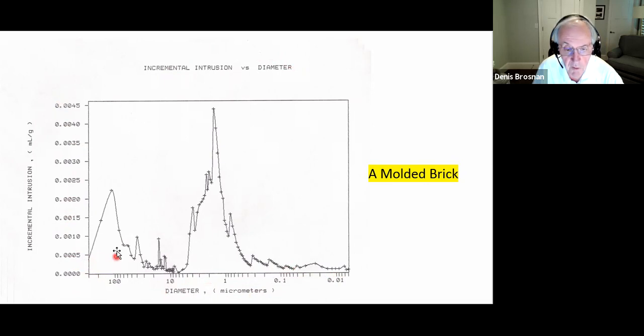If you look at this in increments, we can see that at fairly large pore sizes in this particular brick, we had a band of pores around 100 microns. And as we got down to the smallest band in the area of 1 micron or so, less than 10 microns, we got a large band. Very typical for a brick product. This is a bimodal pore size distribution. Bimodal means two sizes of pores within the ceramic. Okay, a brick is not a very dense object, and so therefore we maintain some of the fine pores.